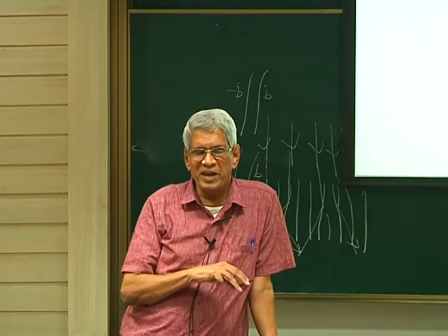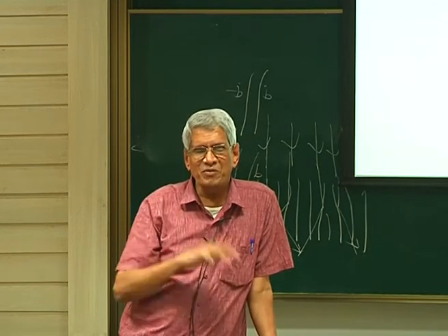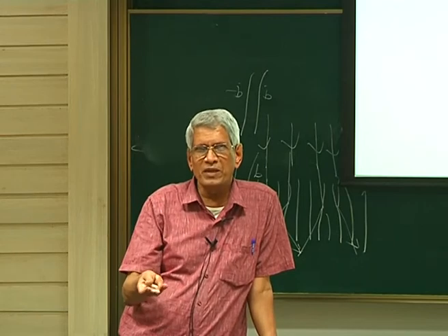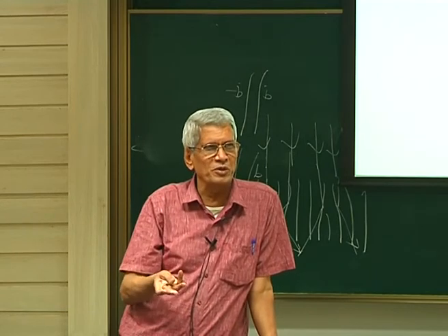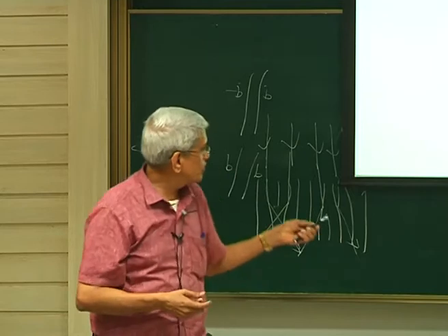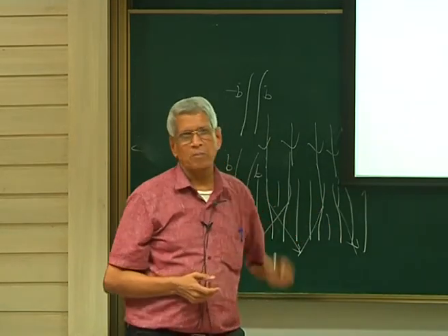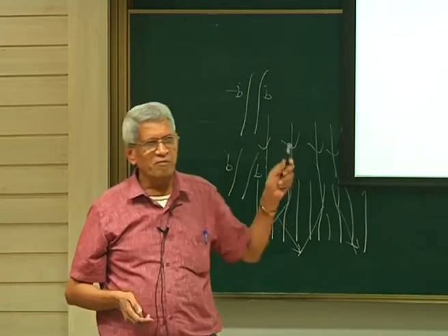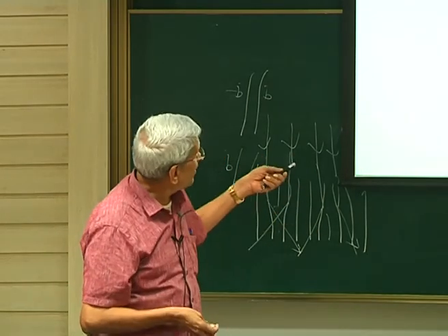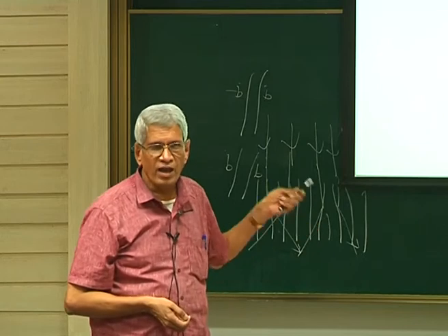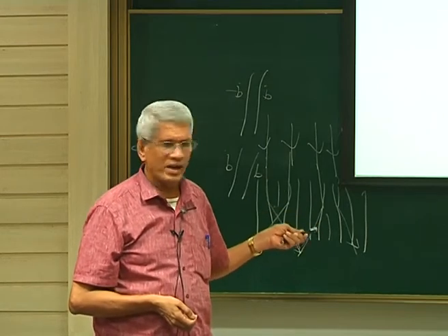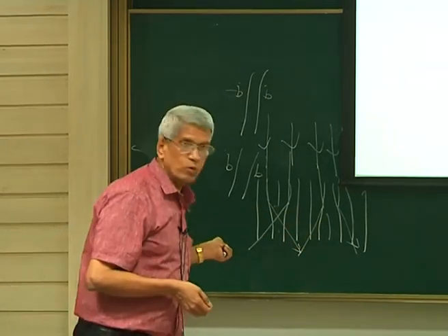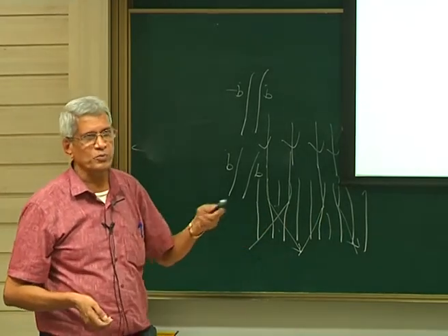So from that we cannot say which has a positive Burgers vector, because G dot B will be 0 and G dot minus B also will be 0. So the only way we can distinguish between them is looking at the separation, okay. This way we can identify whether they are dipoles or pairs of dislocations or groups of dislocations.